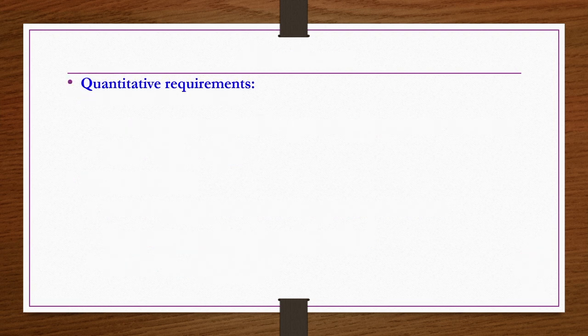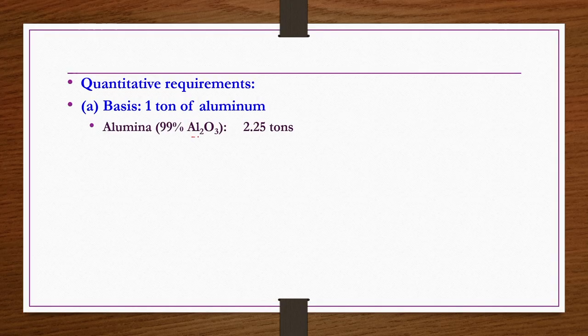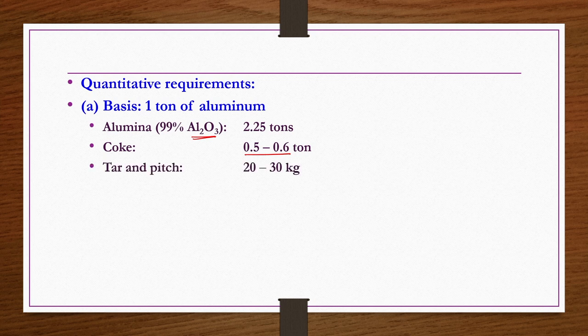If you see the quantitative requirements for the production of aluminum from purified alumina, if you want to produce 1 ton of aluminum, then of 99% pure Al2O3 you require 2.25 tons, and coke 0.5 to 0.6 tons. These reactions are taking place at electrode surfaces, so the electrodes are being consumed. In order to make up the electrodes continuously, or periodically replace them, you need new electrodes. These electrodes are made of tar and pitch, for which you need 20 to 30 kgs of tar and pitch. Cryolite flux, you require 40 kgs, and then direct current electricity, 22,000 kilowatt hours.